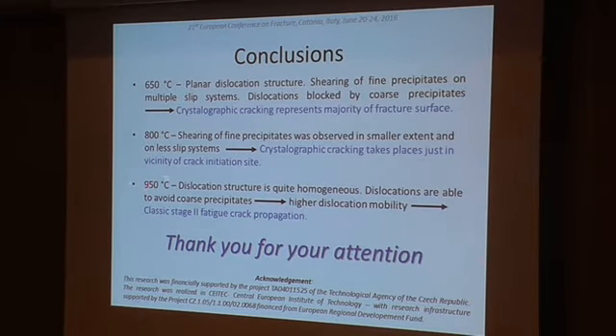At temperature 950 centigrades, the dislocation structure is quite homogeneous. Dislocations are able to avoid coarse precipitates already because of high dislocation mobility, and therefore we observe classic stage 2 fatigue propagation.